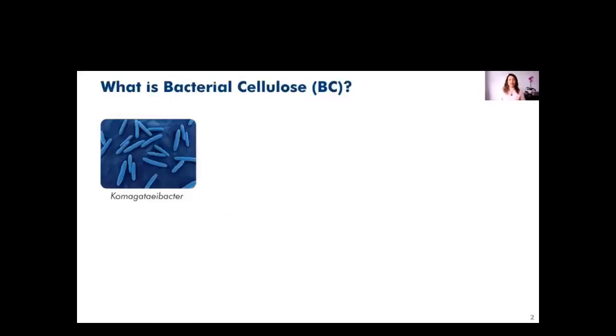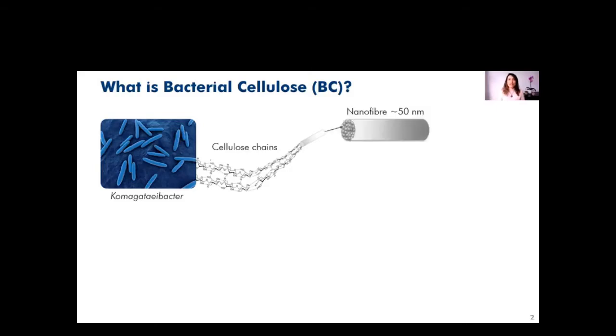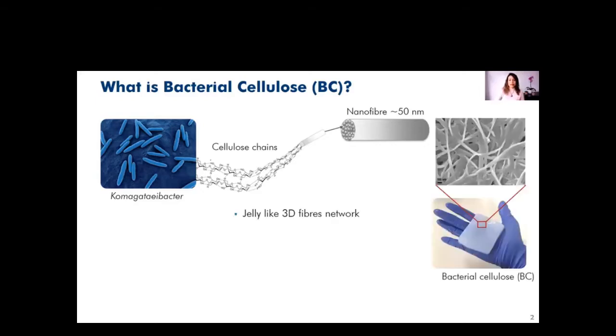So what is bacterial cellulose? Bacterial cellulose is produced from a bacteria that, when it's fed with sugar, produces glucose molecules, and these glucose molecules produce cellulose chains. The cellulose chains together form small fibrils with a really small size in nanometers, and these fibrils come together to form nanofibers of approximately 50 nanometers. The nanofibers grow together, forming a network, and it looks like this image on the right under the microscope.